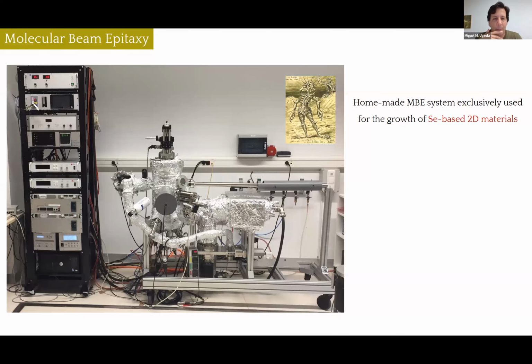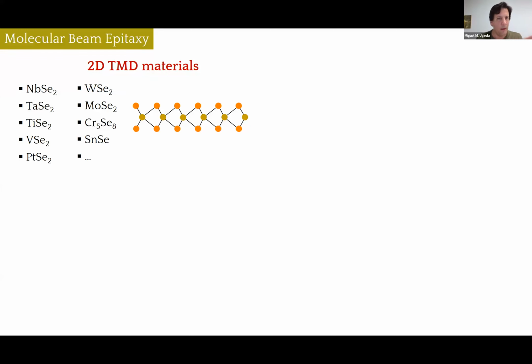So here you have a picture of our homemade molecular beam epitaxy, in which this is where everything starts, right? Because here's where we grow all our 2-dimensional materials. This is a system which is particularly designed to grow only selenium-based 2D materials in order to avoid any cross-contamination. So we only grow TMDs, or at least selenium-based materials. But once we have grown these materials, we basically cut them and take them in general to many other characterization regions. And of course, we've been able to grow very different 2D TMD materials, such as, for example, superconductors, charge density wave materials, but also semiconductors, even ferroelectric materials.